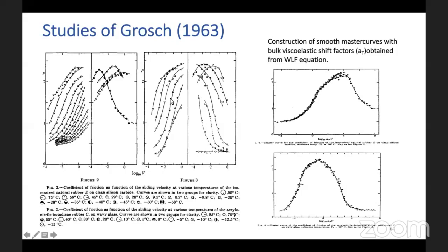What he did with these raw data is that he used bulk viscoelastic shift factors. In the earlier slide, I showed you an equation called the WLF equation. The scientist Grosch's brilliance was that he showed that these curves can be shifted by the same shift factors that govern the shift of the viscoelastic materials to form a master curve. With the same shift factors, he obtained a friction master curve, and this showed for the first time that friction results from the energy dissipation taking place in the bulk of the rubber.